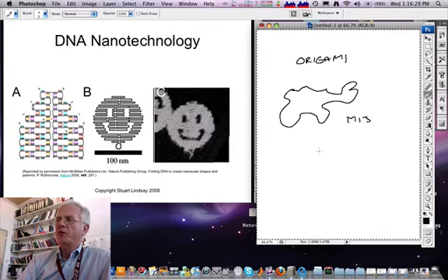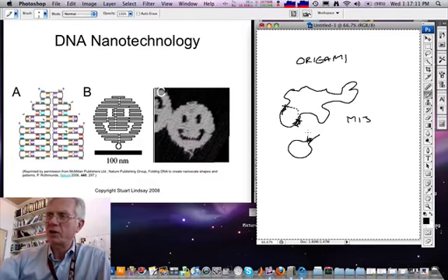And so you say, how would I want to fold this to make a given nanostructure? Well, supposing part of the process is wanting to cross-link this piece to this piece. Of course, you want to introduce many cross-links for the final structure, but supposing that was one of the steps. One could take a small piece of DNA that formed a double helix here by base pairing, and then, I'm showing a dashed line because the structure is not yet folded together, anneal with this over here to form a second double helix. So now the structure would look like this, where you have a little loop like this hybridizing across the structure.